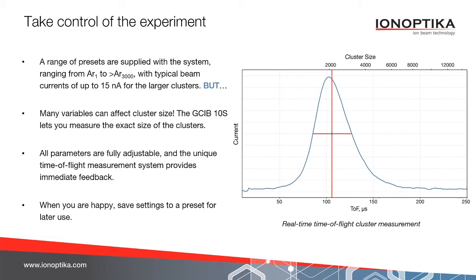However, many variables can affect cluster size. This includes temperature variation, movement in the source region, so the cluster size you think you are getting may not actually be the cluster size you are getting. And we have found that cluster size is a very important parameter for achieving the best results. So knowing exactly what your cluster size is allows you to make adjustments to your experimental parameters to make sure that you're not sputtering too much or too little.